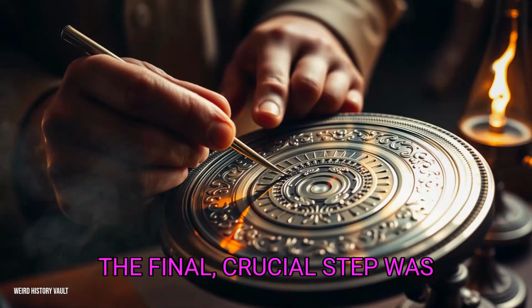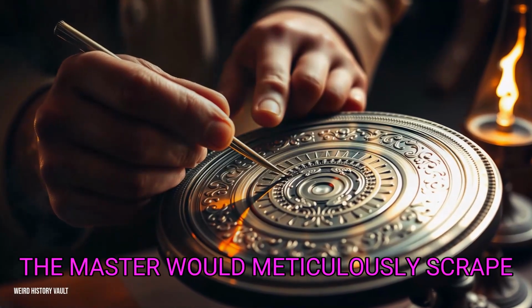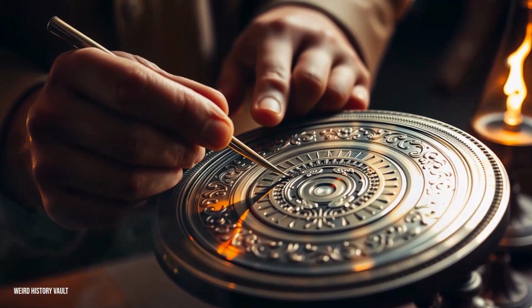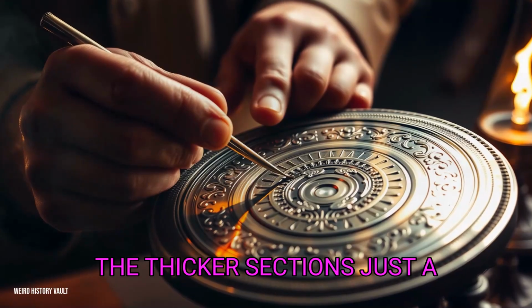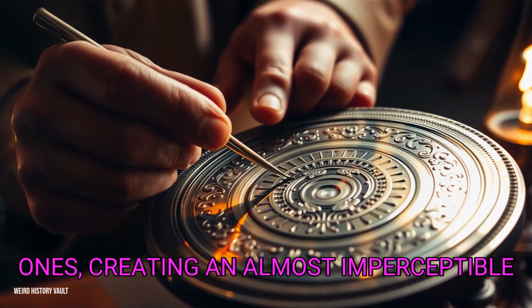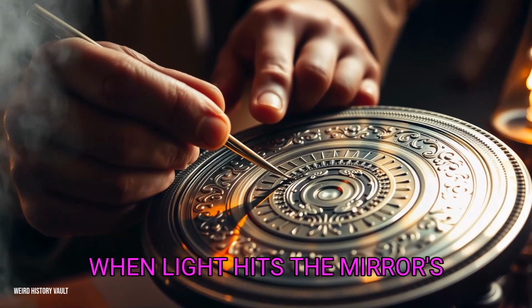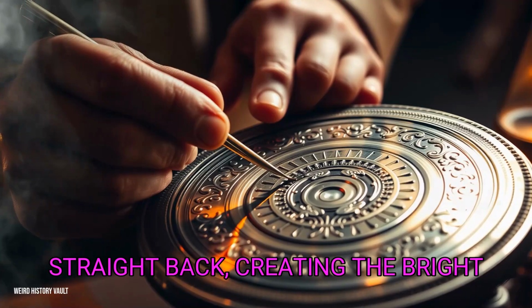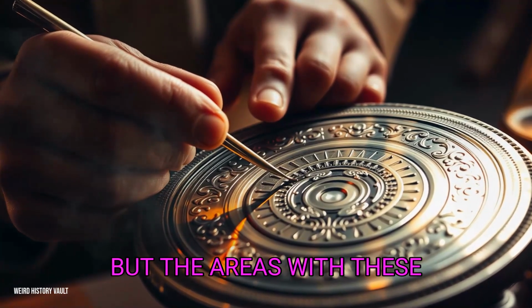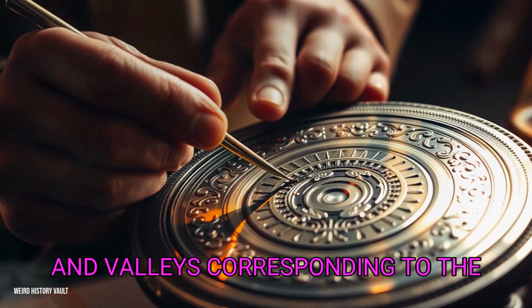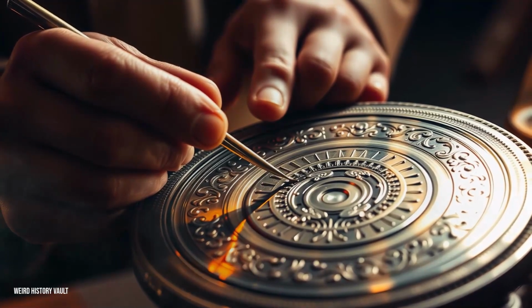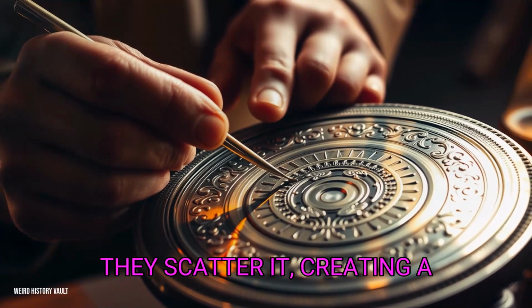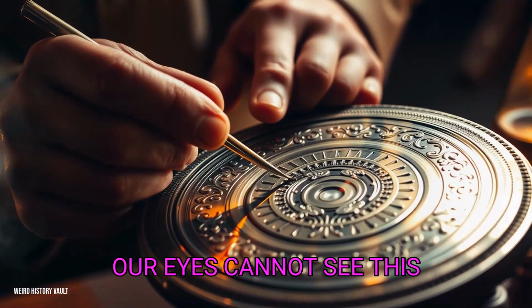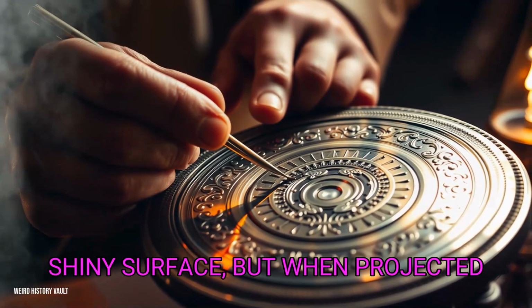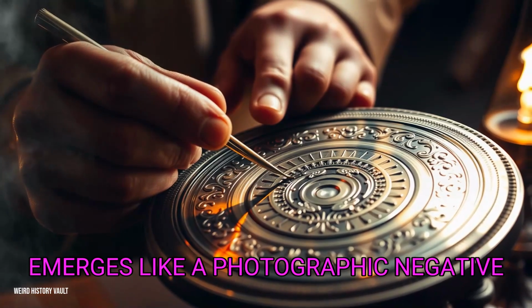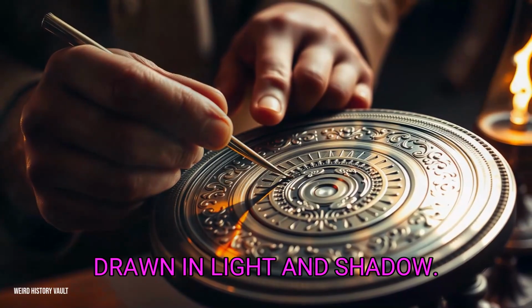The final, crucial step was the scraping. After the mirror was cast, the master would meticulously scrape the reflective face. It is believed they scraped the thicker sections just a fraction more than the thinner ones, creating an almost imperceptible curvature. When light hits the mirror's face, most of it reflects straight back, creating the bright disk. But the areas with these microscopic curves, these subtle hills and valleys corresponding to the hidden design, bend the light differently. They scatter it, creating a slightly dimmer pattern. Our eyes cannot see this subtle difference on the mirror's shiny surface, but when projected onto a wall, the pattern emerges like a photographic negative drawn in light and shadow.